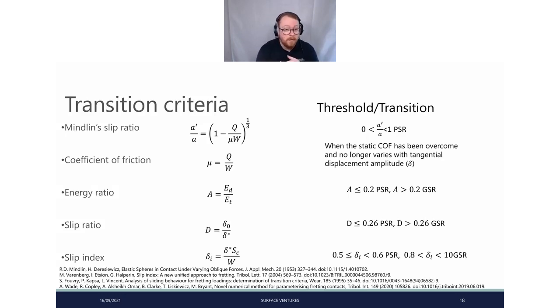We've got quite a few. So Mindlin's slip ratio, which was the earliest of these, basically giving us what would be the transition for partial slip. We can also think about a transition in terms of coefficient of friction. Once our static coefficient of friction is overcome, we can look at it transitioning from a more stick-driven process to a more sliding-driven process. We have energy ratio. Lower than or equal to 0.2, we're in partial slip. Higher than that, we are in gross slip.